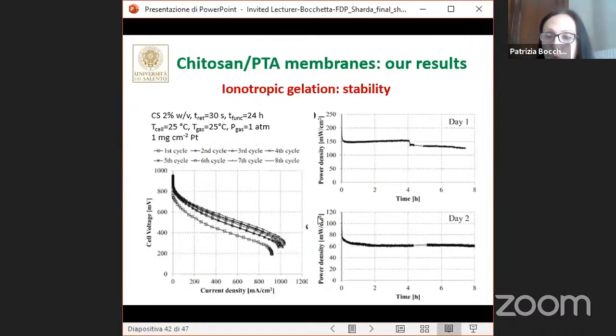In the last slides, I show you some preliminary results about stability. We are continuing to study this aspect. This aspect is really crucial, obviously, for application of these membranes. From these preliminary results, you can see that the power output under a constant voltage of 0.45 V shows that after a decrease during the first 10-20 minutes, the power density reaches a constant value for a few hours. From the figure, it can also be observed a good dynamic stability of the cell, which is able to restart after 12 hours off.